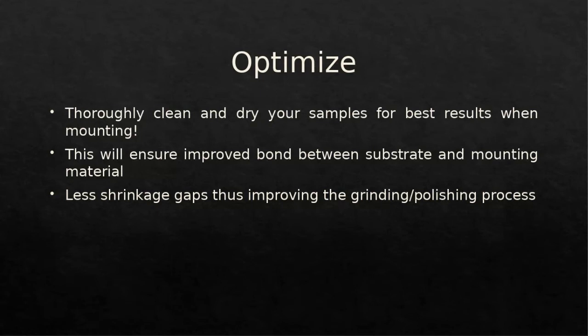For the cleaning process, typically after I cut something, I always ultrasonicate the sample for no more than 30 seconds in ethanol. Okay, ethanol is much better. Do not use methanol. I use ethanol for everything. It's really nice because you ultrasonicate it for 30 seconds. The sonicator will help break up even any loose debris you might have on your sample from the cutting process. And then when you go to mount, you don't have anything prohibiting that media from being right up next to your sample to help improve your edge retention.